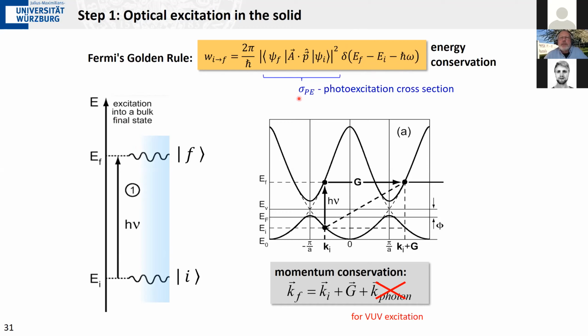When you analyze this photoexcitation cross-section or this matrix element in more detail, you will see that we have momentum conservation, namely that the final state momentum is identical to the initial state momentum, as long as we are in the dipole approximation, modulo a reciprocal lattice vector, so we may have such a vertical transition, or we may have a transition into the next Brillouin zone or the following Brillouin zone and so forth. And in principle, we also have to take into account the momentum of the photon, because that in principle can also carry momentum. Now for low photon energies in the VUV regime, say 20 to 100 electron volts, this can be neglected. This is less than 1% of the typical Brillouin zone extension.